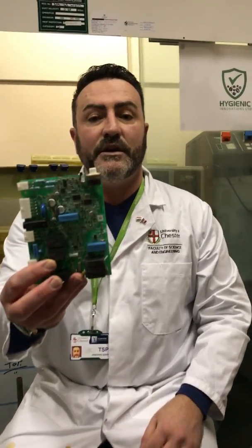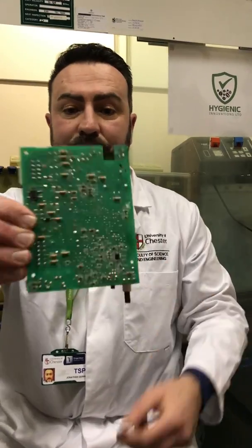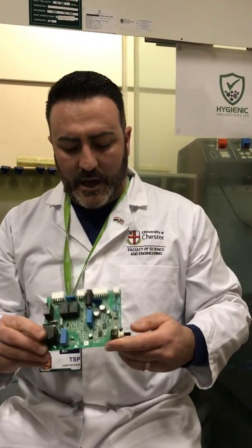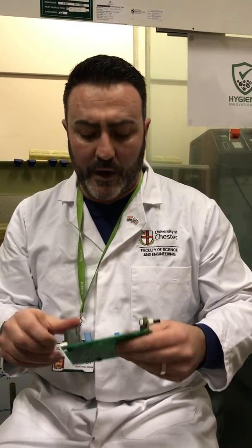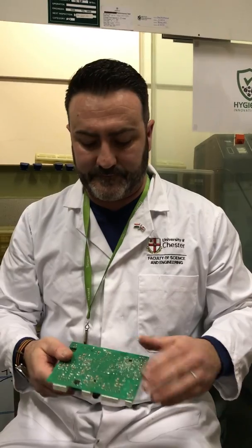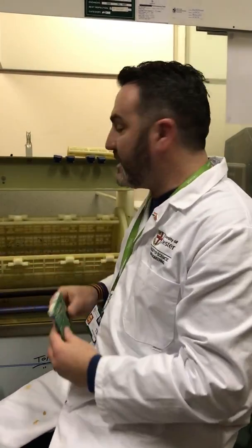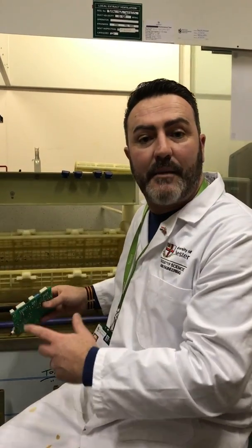Now, the exact same chemicals and exact same technology also works for printed circuit boards. Predominantly, all the components on the board are kept on by solder. So what our process does is, we put the printed circuit boards into the tumbler. They can either be shredded up or be whole on a much bigger system. This is just a lab size. We're currently building a pilot plant size, which will do around 200 kilograms per hour. We put it inside the cage, lower it into the chemicals, rotate the tumbler and put the ultrasonics on.